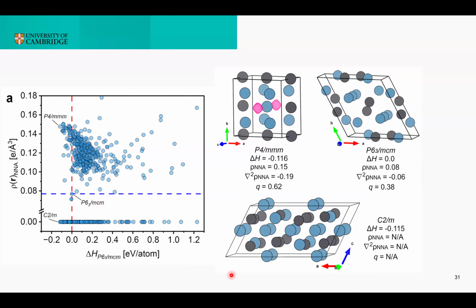On the non-electride side, I also found this monoclinic C2/m phase, which is almost as energetically stable as the P4/mmm, just slightly less stable. But indeed, this one was not an electride. And therefore, this method can easily quantify whether a structure is a good electride candidate. But does it accelerate the discovery of electrides? So are electrides found more rapidly than non-electrides?